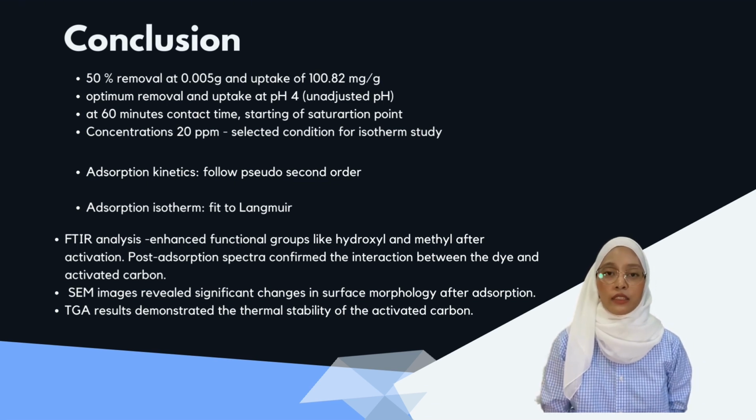The adsorption kinetics followed the pseudo second order model, indicating chemisorption as the primary mechanism. The adsorption isotherm data fit the Langmuir model, suggesting monolayer adsorption on a homogeneous surface. The FTIR analysis showed enhanced functional groups like hydroxyl and methyl after activation. After adsorption, spectra confirmed the interaction between the dye and the activated carbon. SEM images revealed significant changes in surface morphology after adsorption. The TGA results demonstrated the thermal stability of the activated carbon.